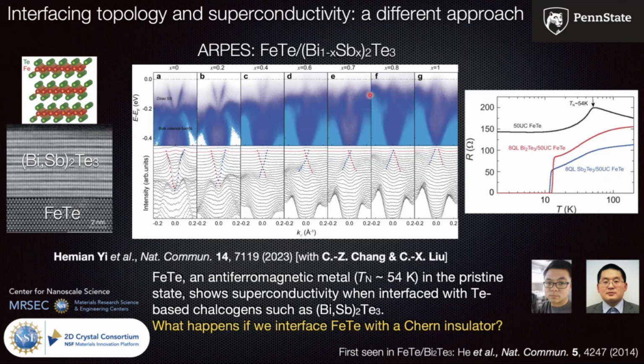So we had this postdoc. He decided to reproduce this experiment, but reproduce it in a way where he could change the chemical potential. So he grew bismuth antimony telluride on iron telluride. Here is the ARPES data taken in our facility. And on the right-hand side, you see the resistance versus temperature, showing the superconducting transition. And this is a nice paper in which we've tried to make a case for why, as you change the chemical potential, the Tc changes as it does, and so on.